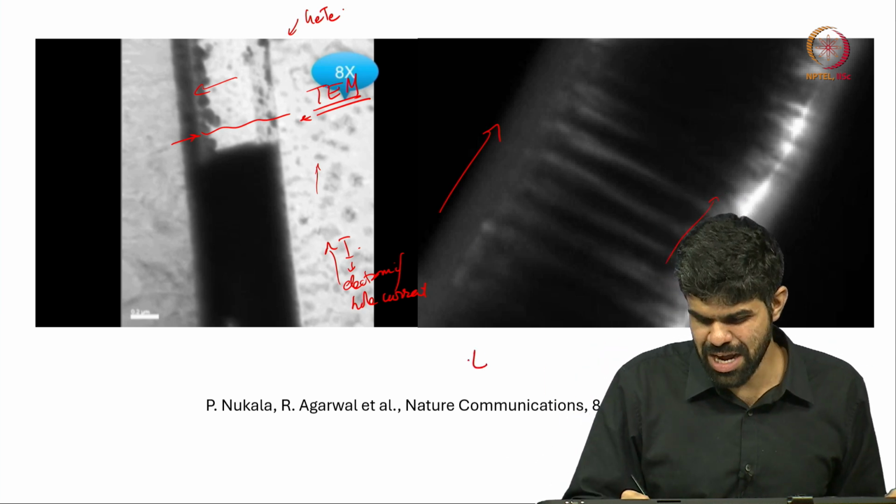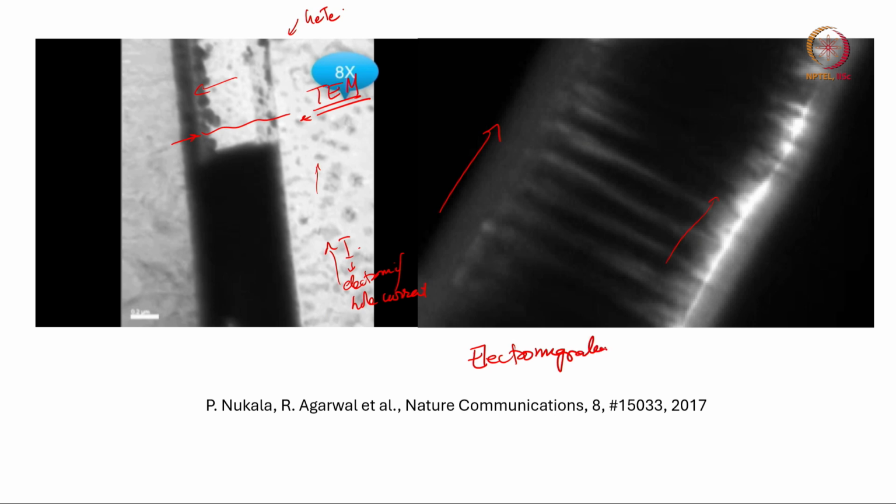So these are examples of what is called electromigration. Here in this case, because of something that I do, this is more sort of controlled electromigration. Here in this case, it is sort of uncontrolled electromigration. It is the same wire, right, depending on how I apply the initial bias, right. So whether I send in large current continuously or whether I send in pulses of current, right.